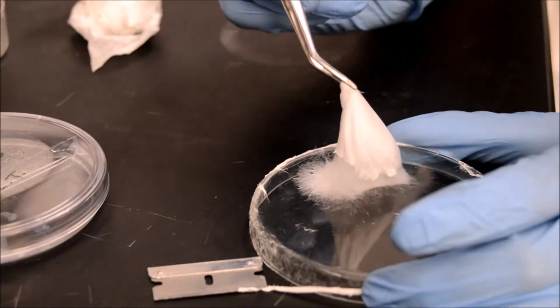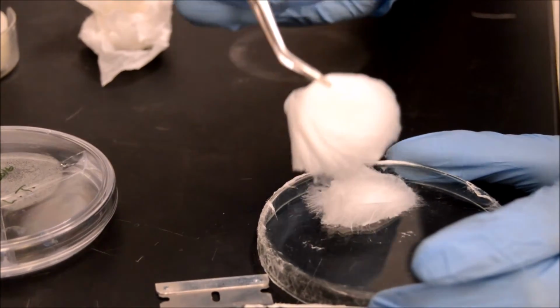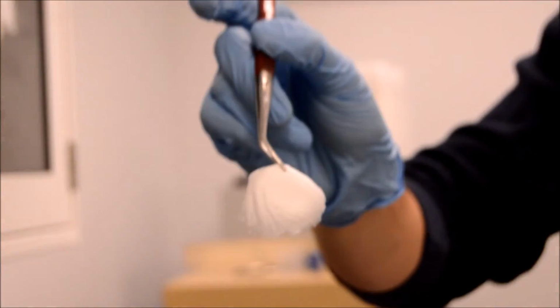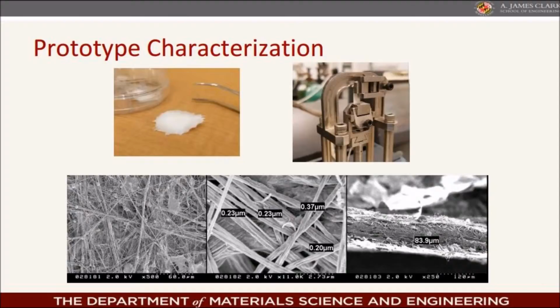In the initial round of prototyping, mats were deposited using 5 weight % PLA in THF. We characterized the mats using a scanning electron microscope and confirmed a nanofiber morphology with diameters ranging from 200 to 400 nanometers. Dynamic mechanical analysis, or DMA, was used to characterize the mechanical properties of the non-woven mats, and this data was used to improve the accuracy of our models.